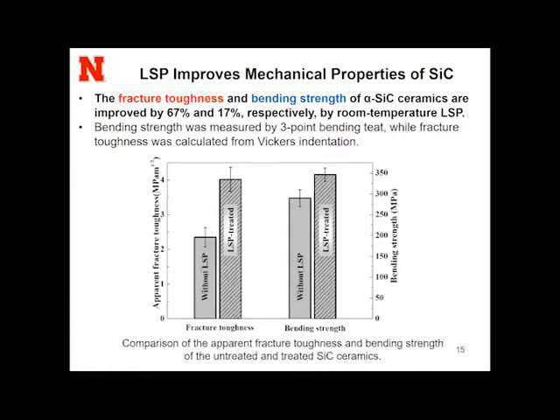And we can quantify the results here. The fracture toughness is measured this way, and the bending strength is measured by using the traditional 3-point bending test, in which we do the laser shock peening on the whole surface of the bending bar. And we found that both fracture toughness and the bending strength are significantly increased in the silicon carbide after laser shock peening.